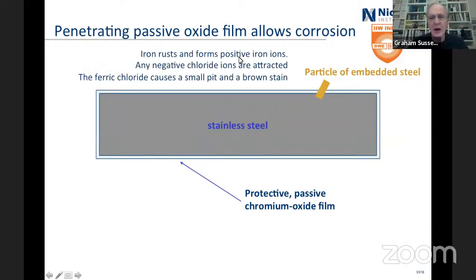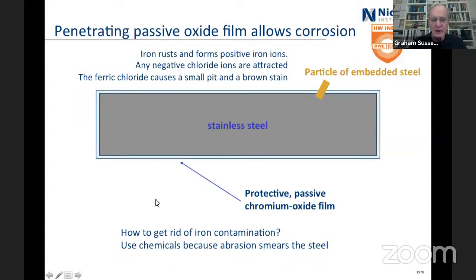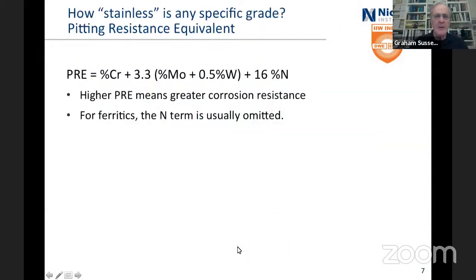That will release ions, which are positive. If there are chlorides around, they get attracted towards it. And so you wind up effectively with a ferric chloride solution around that spot, and you'll get a little rust spot. You'll get a micrometer deep pit, which isn't anything to worry about, except you're worried about having a nice bright piece of stainless steel. So you get rid of it. How do you get rid of it? Well, use chemicals, because if you abrade it and polish it, then all you're really going to do is smear the steel that's left on the surface, and you get a bigger smear.